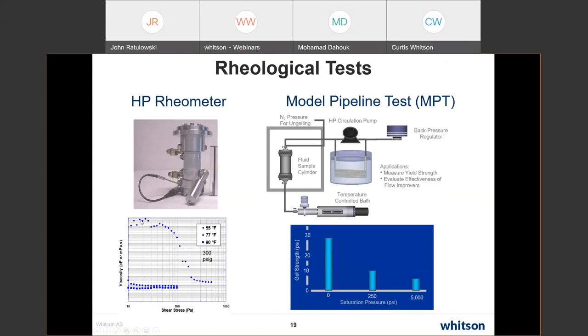Looking at gel strength, a lot of times we can also use a rheometer to do this, but in the past, both at Shell and DBR, we used something called a model pipeline test, where you would fill a coil with oil, and then you would gel it using a temperature profile or a temperature history that you thought was representative of the field. And then you just measure the pressure required to restart or move that gel.